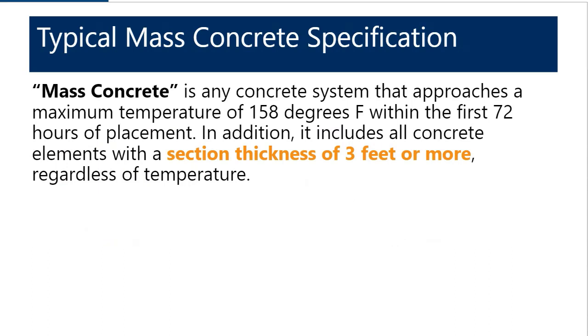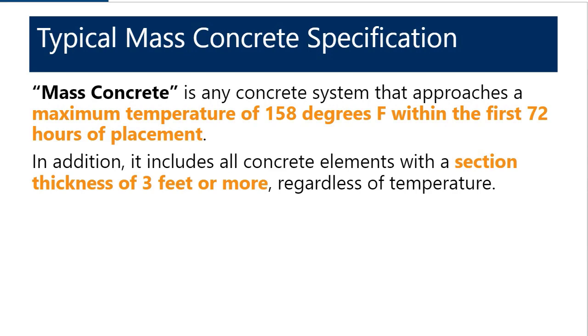And so here's another specification that we've dealt with. This particular specification, just like the last one, requires all elements with a section thickness greater than 3 feet or more to be considered mass concrete. But it also includes a portion that says that it's any system that approaches a maximum temperature of 158 degrees Fahrenheit within the first 72 hours. And that way, it can also include elements that are thinner than 3 feet that may have other reasons for that heat gain, whether that's related to the environmental conditions, the concrete mixture proportions, or the boundary conditions, or any combination thereof.